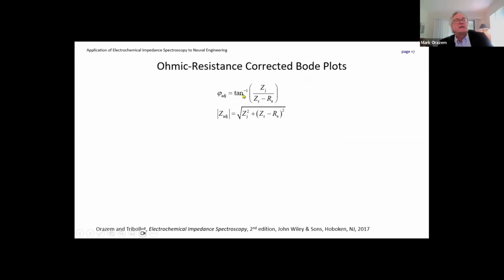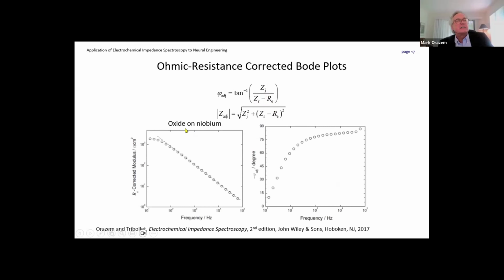So the phase angle is the inverse tangent of the imaginary part divided by the real part. So what we'll do here is to subtract from the real part the ohmic resistance. We can do something similar for the magnitude. So if we're looking at the oxide on niobium, what we see in the phase angle plot, which is here, is that we do not really see a constant phase. So this would tell us that oxide on niobium does not have a constant phase element behavior.